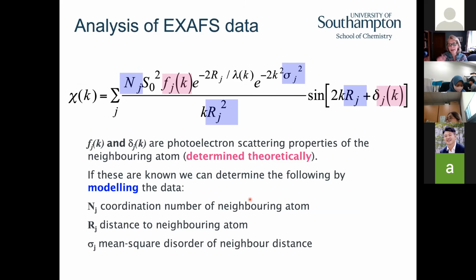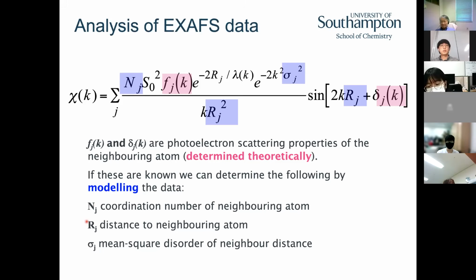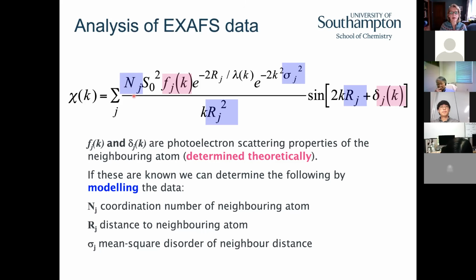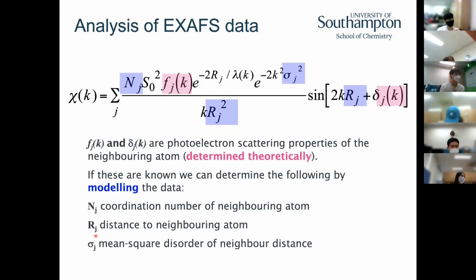To analyze those wiggles in the EXAFS, we have to fit that data to this equation. And I'm not going to go through the equation in great detail. I just want you to recognize the parameters that we are fitting. So we're fitting the coordination number here. So we know how many neighbors of that type are surrounding our absorbing atom, or absorber atom. We know the distance to them, that's here and here in the equation. And then we have a mean square disorder.